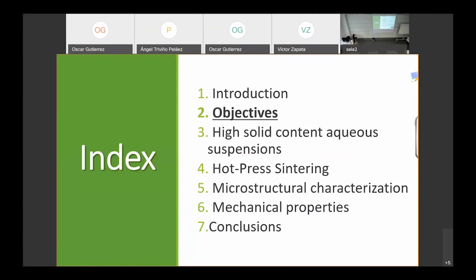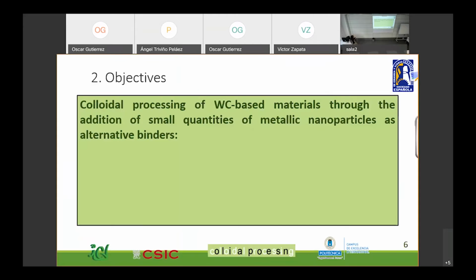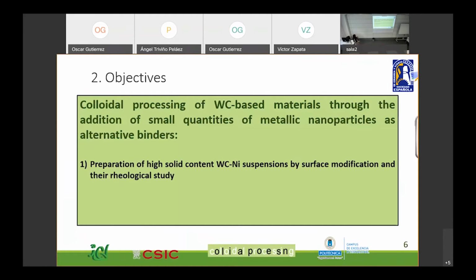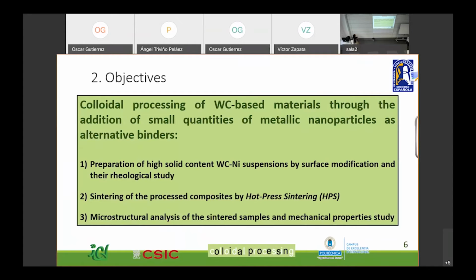So after this introduction, we would say that the main objective of this work is the colloidal processing of tungsten carbide-based materials through the addition of small quantities of metallic nanoparticles as alternative binders. How did we do that? Well, first, by the preparation of high solid content tungsten carbide nickel suspensions by surface modification and the rheological study. And after that, by the sintering of the processed composites by hot press sintering. And finally, we studied the microstructure and the mechanical properties of the final materials.